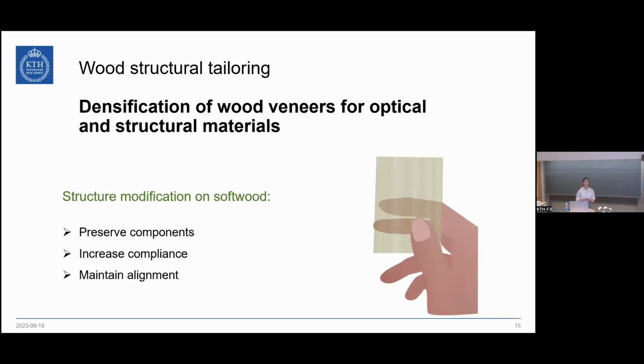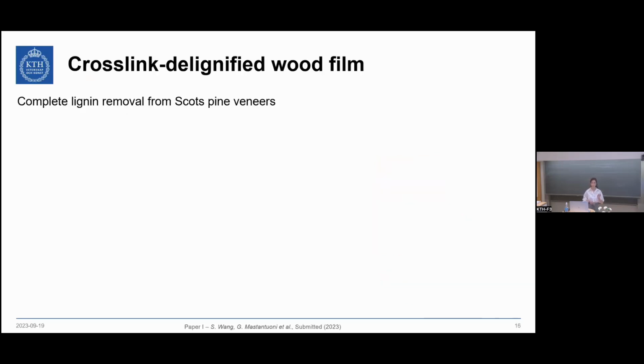And what we wanted to do was instead to work on softwood and to try to preserve the components as much as possible. At the same time, we did need to modify the structure. So in this case, the structural tailoring needs to find a balance between increasing the compliance so that the material could be easily densified, while at the same time maintaining the alignment of the wood fibers, so as not to disrupt the orientation, so that uniaxial mechanical properties can actually be improved. In the first approach, to increase compliance, what we wanted to do was to remove lignin from the wood structure.